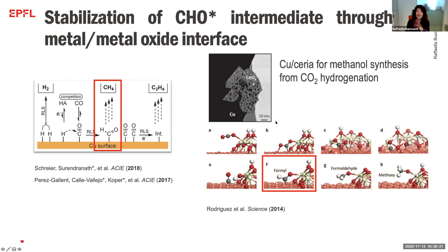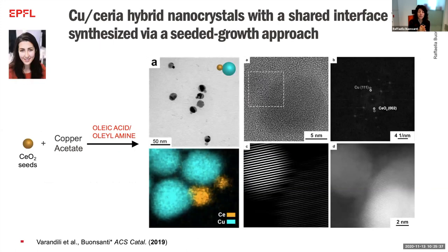Now, we cannot directly translate this catalyst to electrochemical CO2 reduction because if we have big particles of oxide, we cannot have electrons going through easily. So we have to miniaturize the system, basically. And this is what Denaz did. She basically created these catalysts, which are constituted by a sphere of copper and a sphere of ceria. And they really share an interface between them, despite the existence of a high lattice mismatch.